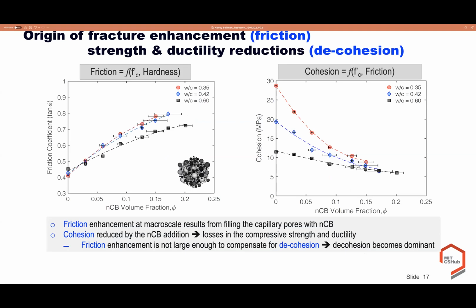This is why we're moving to studying the friction and the cohesion of the material, the two parameters that define the strength. The friction is estimated as a function of compressive strength at microscale and hardness at microscale, while the cohesion is estimated as a function of compressive strength and the friction coefficient. And what we observed here is that the addition of nanocarbon black for the three different water cement ratios leads to enhancement of the friction coefficient of the material. And this friction coefficient enhancement results from filling the capillary pores with nanocarbon black particles.